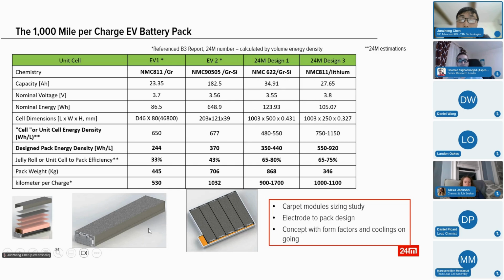With the narrow format lithium metal cells, we reduce the Electrode-to-Pack efficiency, and we reduce the clamping of the structure, to make sure the high pressure can be applied to the lithium metal. We sacrifice a little bit on the Electrode-to-Pack efficiency, but we can still achieve more than half or 1/3 of the weight, and can still achieve around 1,000 kilometer drive very easily. This form factor is still under study with lots of cooling designs ongoing, and we are demonstrating that